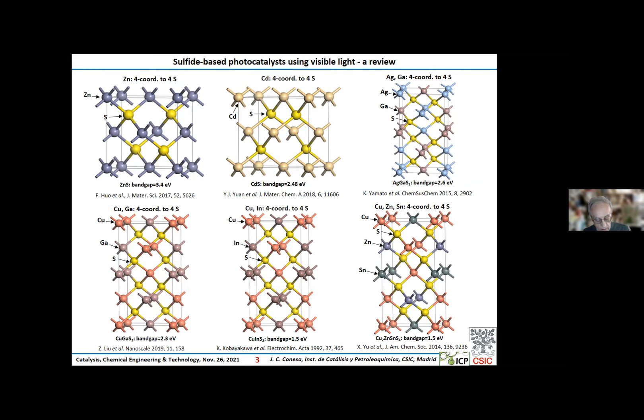I will show later such comparison in slides six and eight. The chalcopyrite silver gallium sulfide, copper gallium sulfide, and copper indium sulfide have decreasing band gaps. Especially the latter, sometimes mixed with the selenide, is used as the main absorber in photovoltaic cells. But because indium is a costly material, the kesterite material copper zinc tin sulfide can be used, which has the same band gap as copper indium sulfide.